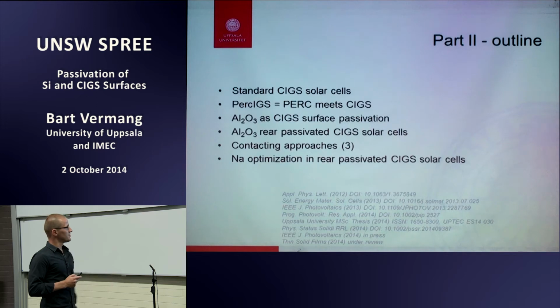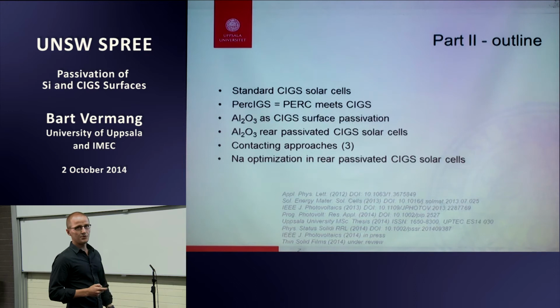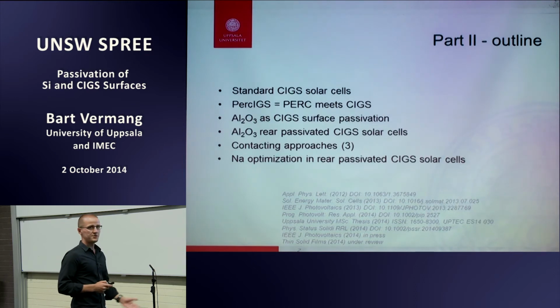Then I will show you some results of the aluminum oxide rear-passivated CIGS solar cells. Again, I'm going to compare to silicon because you see similar things happening, which is a good indication that the passivation approach works. Here, the challenge is to make nano-sized contacts compared to the micron-sized contacts in silicon. So we have, in the meanwhile, 3 different contacting approaches. I'm going to discuss those.